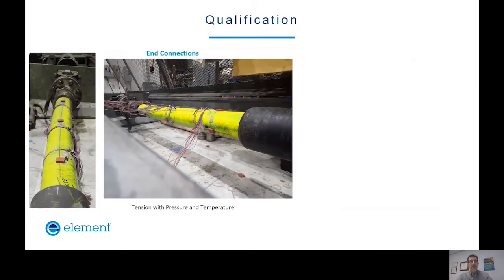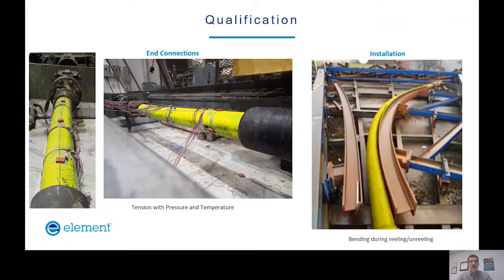So in the product performance, we often not just look at pipe, but we also have to look at end connections and the behavior of the entire product. Here we can see product being loaded up with its end fittings to look at elongation as we pressure up, provide tension, possibly add thermal conditions to it. In addition to those, we look at the longer product as it simulates an installation, both reeling and unreeling. And here we can see the loads being applied, not just the reeling application, but also pressure and potentially an additional tensile load. All these become critically important as the composite product itself is unique. If it's not wound at what's traditionally called a neutral angle, you'll see the product either contract or expand as it's pressured up, which can create interesting reactions at the end connections as we go into the field.